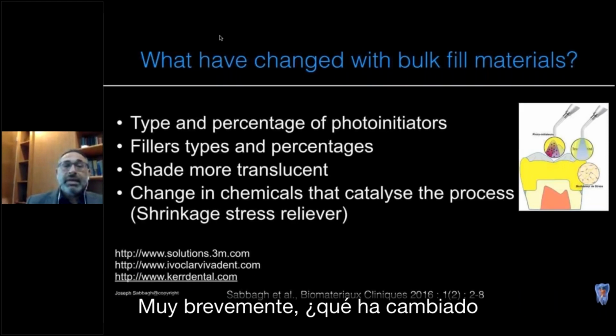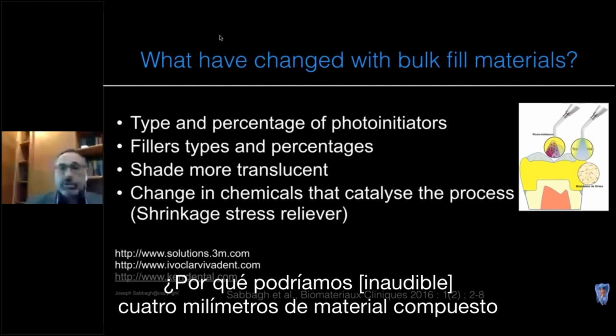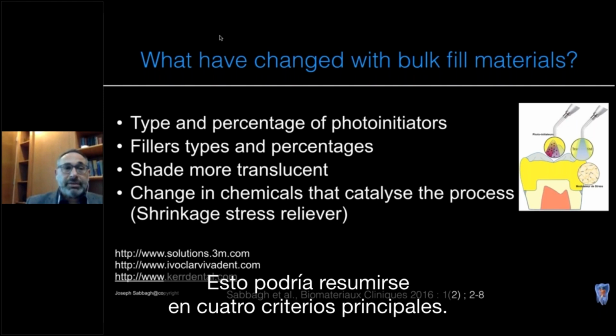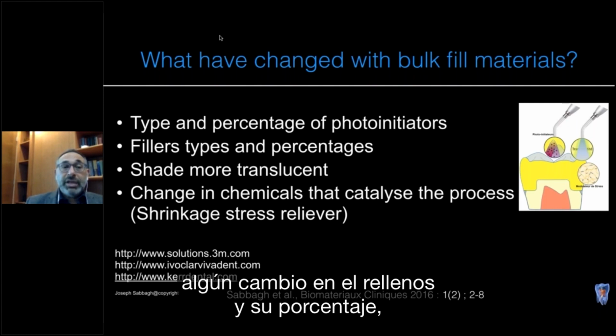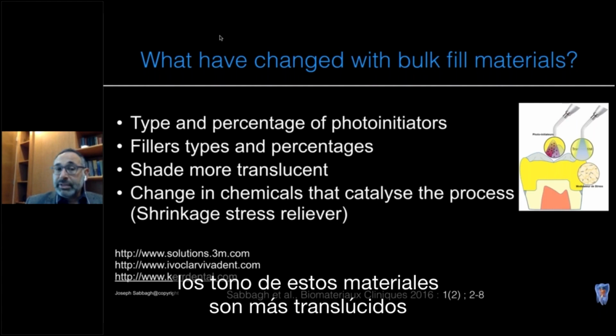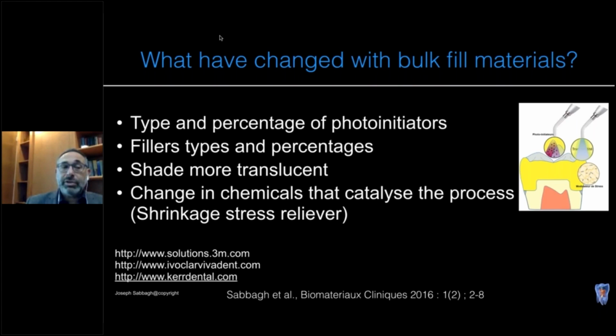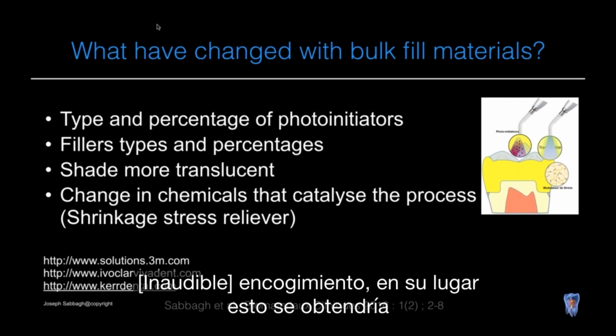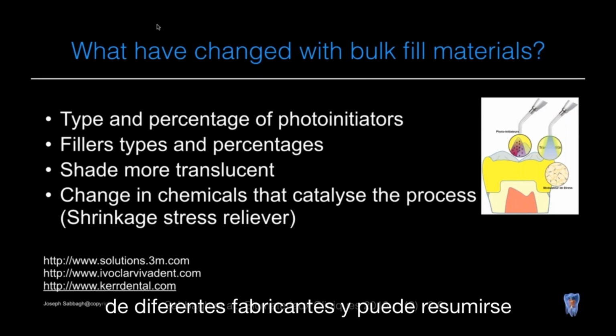Why could we all of a sudden light cure 4 millimeters of composite instead of 2? So this could be summarized in 4 main criteria. First, we had some change made in the type and percentage of photoinitiators, some change in the fillers and their percentage, the shade of those materials are more translucent, better light penetration within this material. This could be gathered from the different manufacturers and can summarize and explain why we could polymerize this material